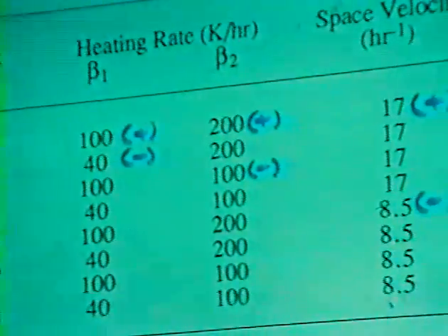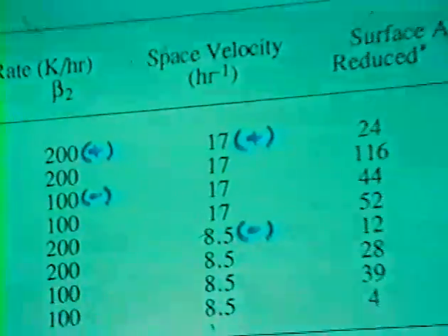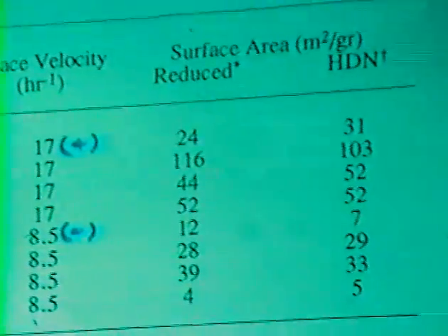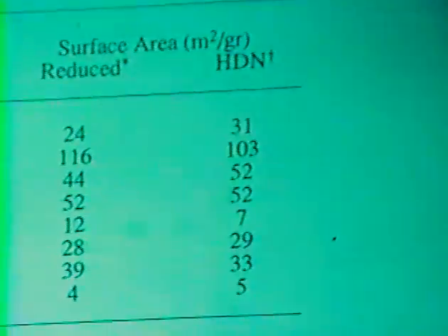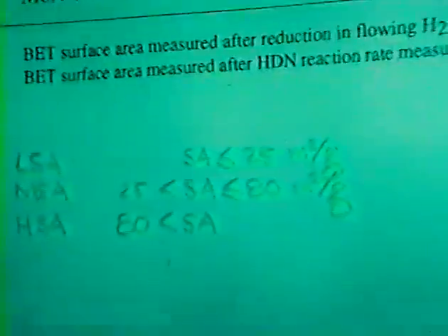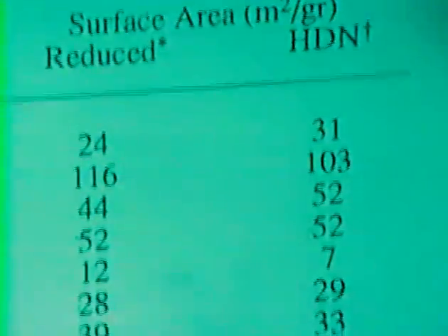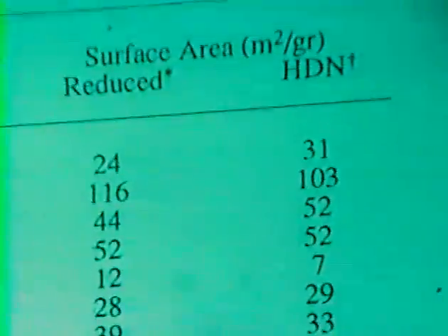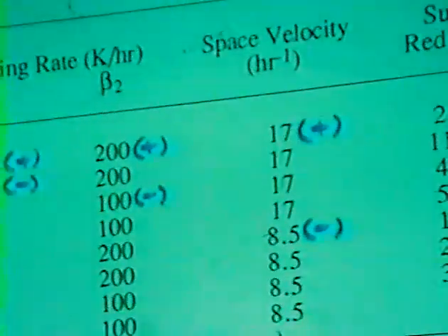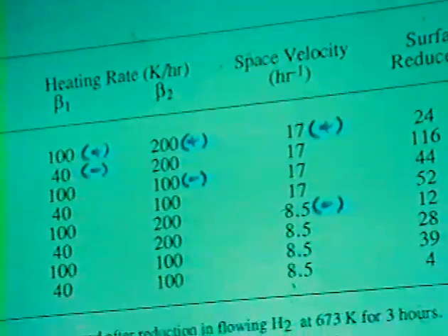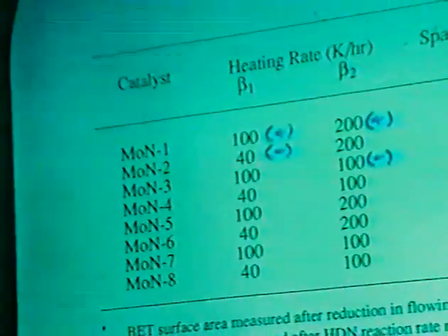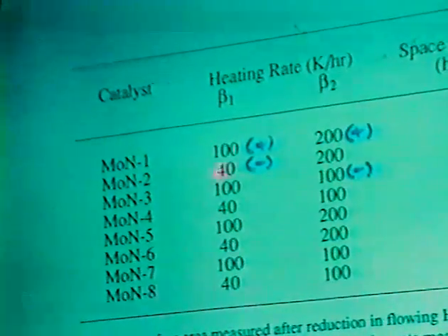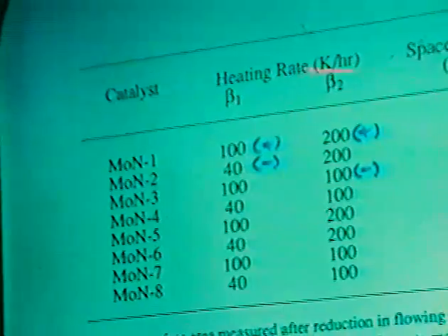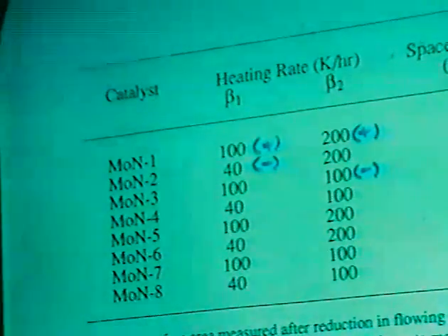In addition to the heating rate, like most other reactions, the space velocity is also important. Here we have listed the experimental parameters that were used. We used a 2^k factorial experimental design to try and guide our experiments. 2 levels, as I mentioned, for beta 1, 2 levels for beta 2, 200 and 100, and then 2 levels for the space velocity. These by no means bracket all of the conditions that were used in either our lab or in other labs to try and create these materials. However, it does allow us to determine in a very efficient manner whether any of these 3 parameters has an influence on the structural properties, and then I'll show you whether those structural properties have any bearing on the catalytic properties.